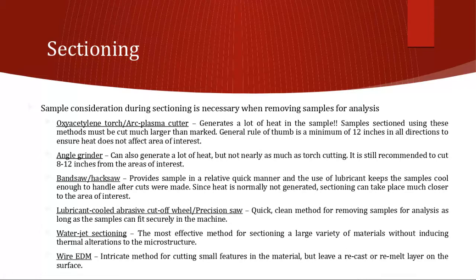Water jet sectioning. This is an important technique, especially if you're dealing with materials that you do not want to induce any type of thermal alterations to the microstructure. High temperature components, for instance turbine blades, would be one that this technique is very useful for. The reason why is because when you're trying to characterize a material that has seen high temperature use, you do not want to generate further thermal damage, therefore altering and/or changing the microstructure, which will then lead to misinterpretation.